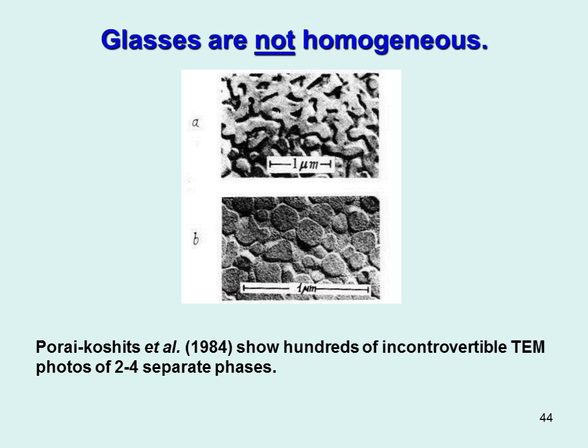The thing that happened on the way to the forum is some Russians, instead of X-ray diffraction, which is a very poor tool for trying to get structure from non-periodic lattices, just took TEM. They're looking at the structure. And what Porai-Koshits, the director of the institute in Leningrad, showed was incontrovertible proof that every transparent looking glass is heterogeneous to beat the band. You look at the different phases. These are pretty big things, tens of nanometers. And you look inside there, even at the bottom diagram, you see that two blobs have come out of different shapes and sizes, and that each of those two blobs have then phase separated within them.